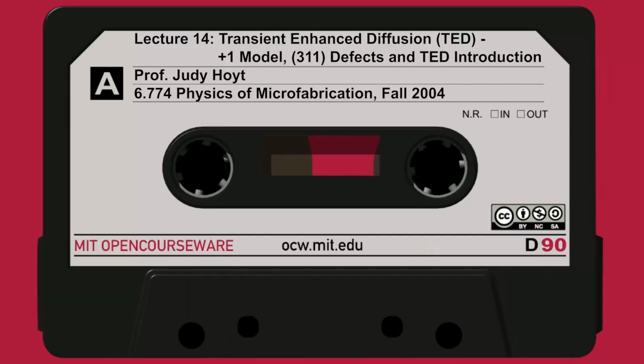For a heavy ion like arsenic or antimony in silicon, the damage is more stable. Okay, so it doesn't tend to anneal out at room temperature. It's relatively easy to form an amorphous layer with a heavy ion at room temperature, and this can then be regrown. We talked about a process called solid phase epitaxy to regrow that amorphous layer.